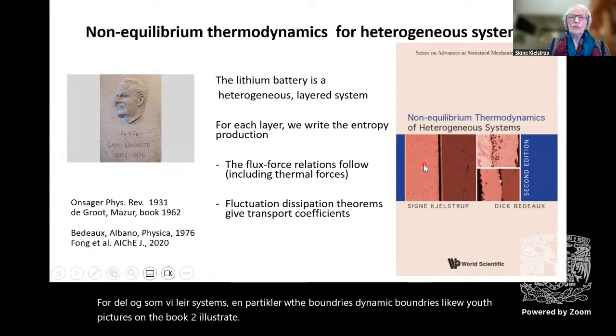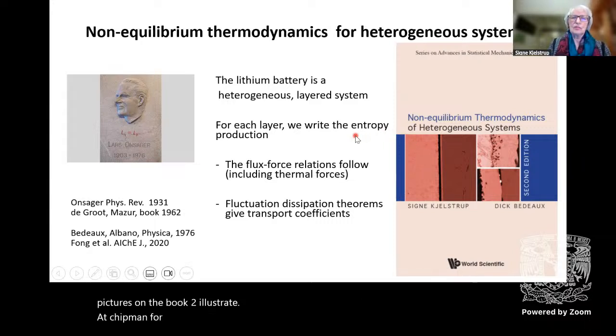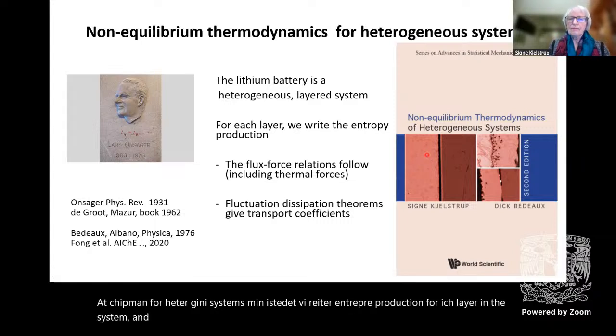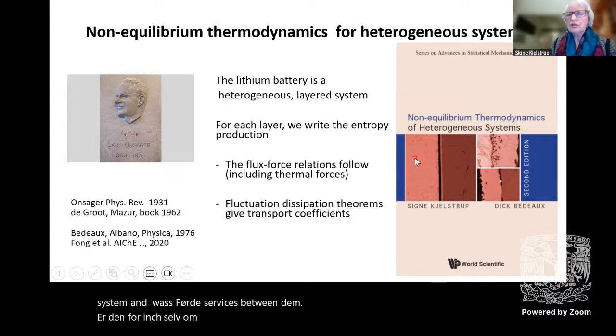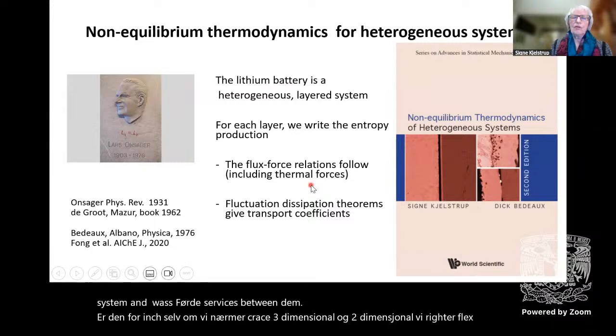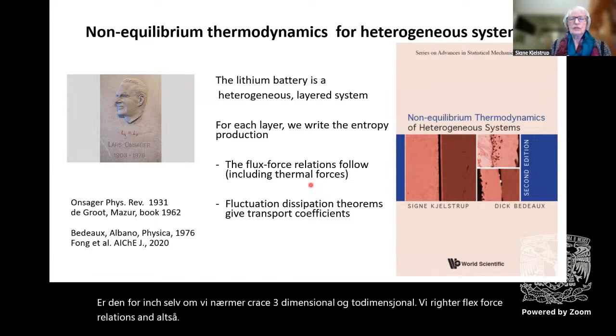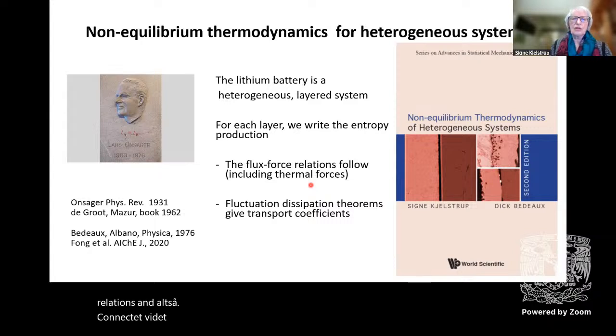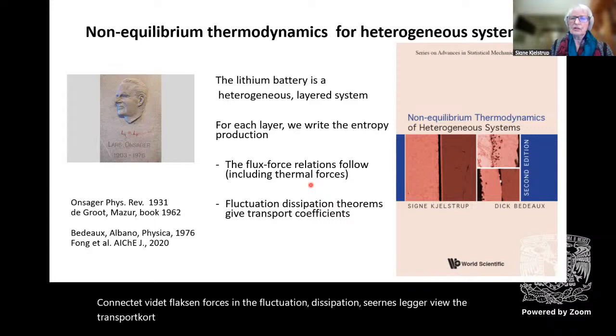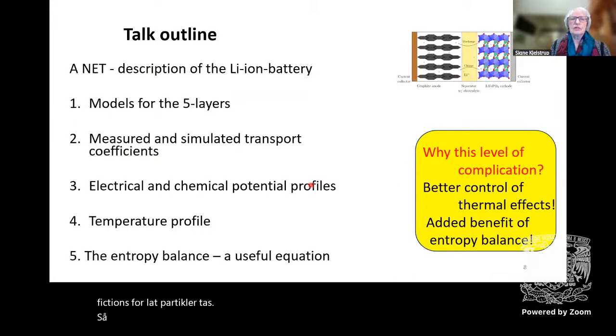So what the treatment for heterogeneous systems means is that we write the entropy production for each layer in the system, as well as for the surface between them. And for each thermodynamic phase, three-dimensional or two-dimensional, we write the flux-force relations, and also connected with the fluxes and forces are the fluctuation dissipation theorems. They give you the transport coefficients for that particular case. So this systematic theory is now at the core of my interest.